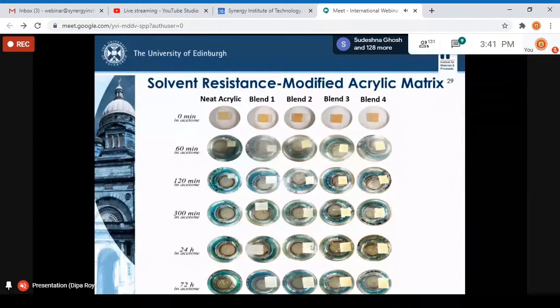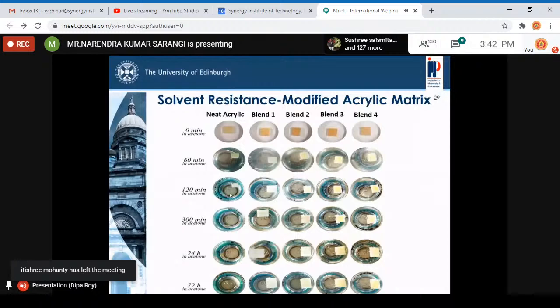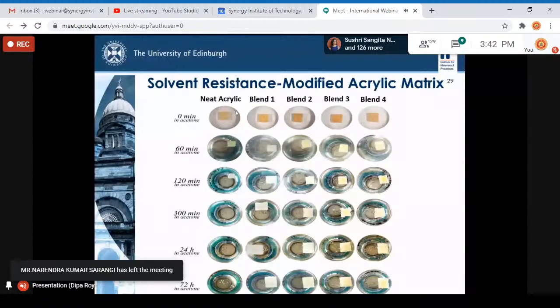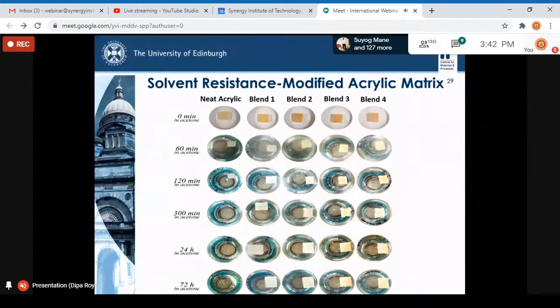Now we did some solvent resistance tests. Acrylic resin is highly susceptible to solvent attack. If we put a neat acrylic sample in a solvent, within 2 to 3 hours all the sample is fully dissolved. So here we have the pure acrylic sample and the blend samples. Within a few hours, the acrylic vanished. It completely dissolved, but all the blends were still there till the end of 72 hours. That was a very positive indication that we are improving the solvent resistance of this matrix, which might be really beneficial when these composites are used in some demanding environment.